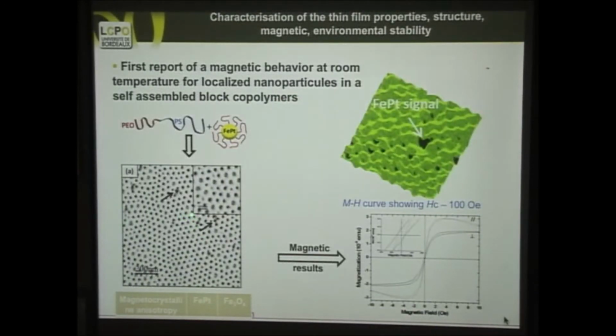So this is what we're going to do. And this is what we prove here with the transmission electron micrograph, that we put 20% of particles here, so that not every spot has a magnetic particle, but a few of them. And we also use the magnetic force microscope now to see exactly where they are. So we saw some of them there. This is the first experiment with a tool made by Bruker that allowed us to go and see it, because they made the magnetic force microscope, which can run very fast, very dynamically.